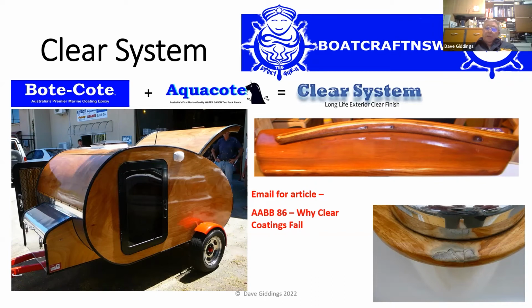When you see the shine starting to dull on the top coat, it means you've got to wash it down with hot soapy water, give it a light sand, and throw a couple more coats of the polyurethane over the top, the acrylic over the top.